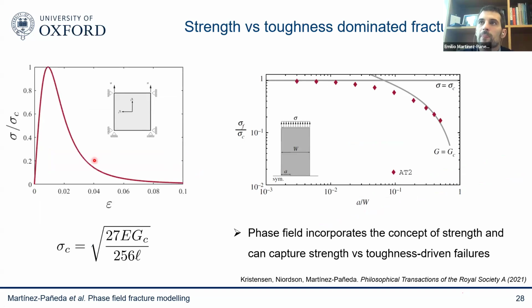And you can see this here. So if you take a 1D example, so you take a homogeneous problem where you forget about the gradients, you can do that analytically, or you could just take a one element problem in Abaqus or in your favorite finite element code and load it. You see that you get this sort of stress strain curve that resembles very much the kind of traction separation curve that you'll see when you use cohesive zone elements. So you see that you increase, and at some point you reach a strength after which you start dropping your load carrying capacity. And analytically, you can find that for the standard AT2 phase field model, there is this relationship between the strength, the toughness, Young's modulus, and the length scale.